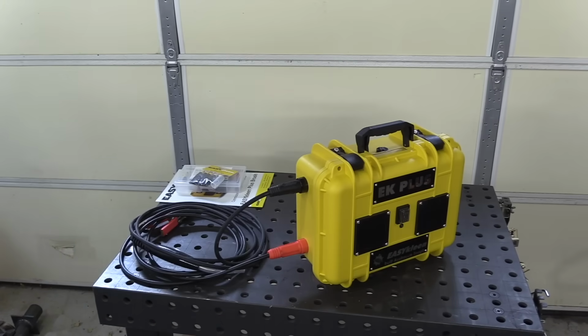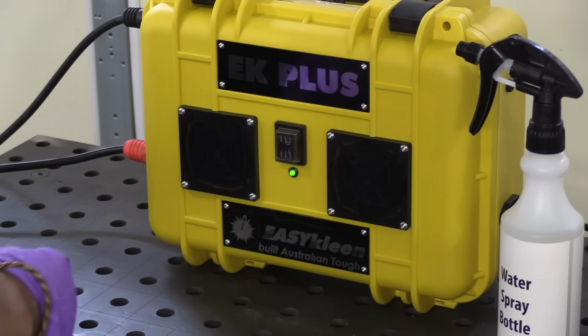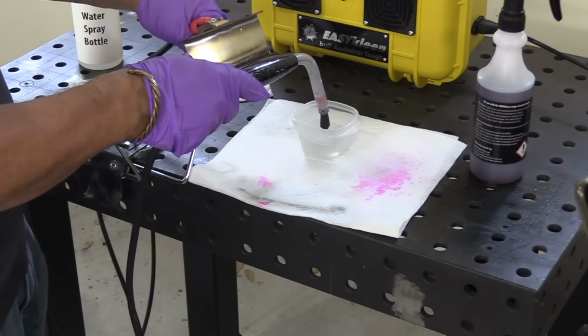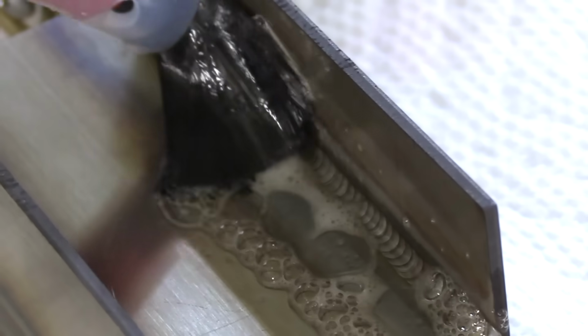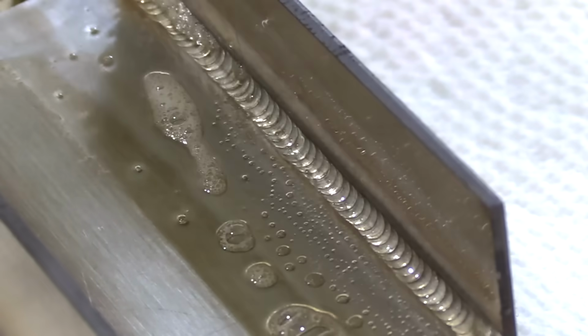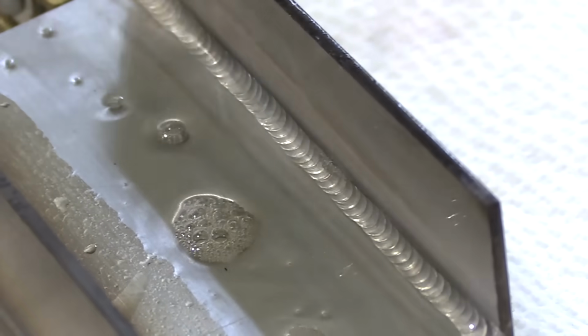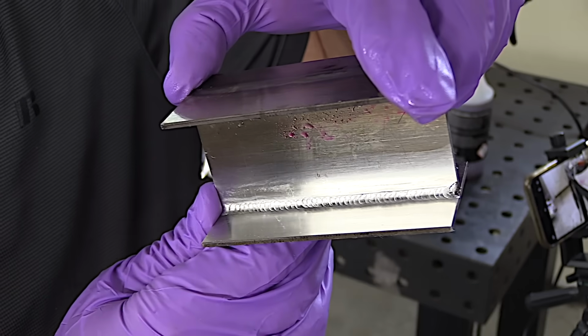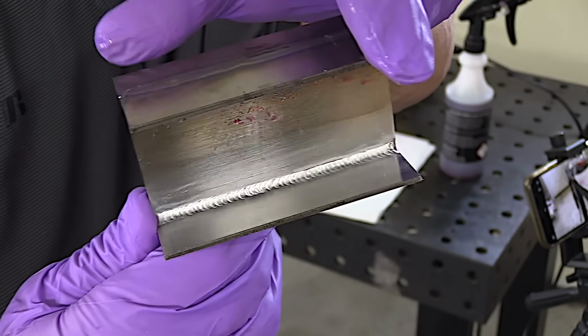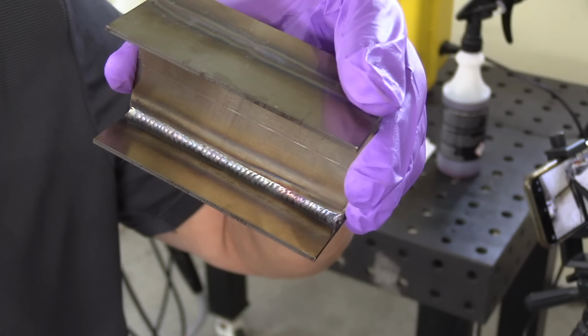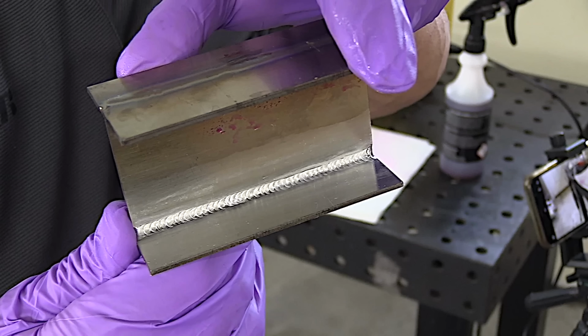So one way to get rid of that oxide layer is with a stainless steel cleaner. This is the Easy Clean EK+. It's an electropolisher that uses a solution here to remove that oxide layer, and actually removes a very small layer of material to where it's very corrosion resistant when you're done. Here's the before, and here's the after. Big difference.